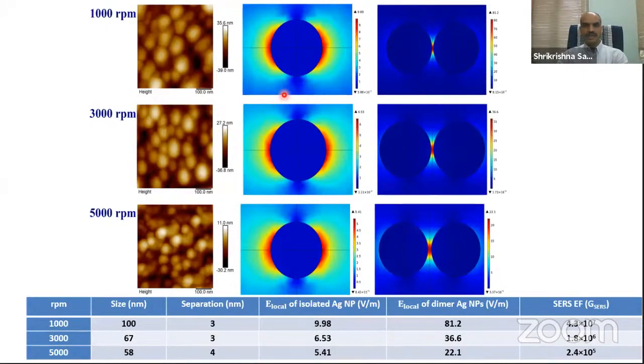So you can see this electric field enhancement for 1000 rpm, this is spin coating, you get a very high enhancement. This is 9.98. It's up to 10 raised to 10. But if you go for 3000 and 5000, these are AFM images, you can see the enhancement is different. So what we have done, we can get this trace detection.